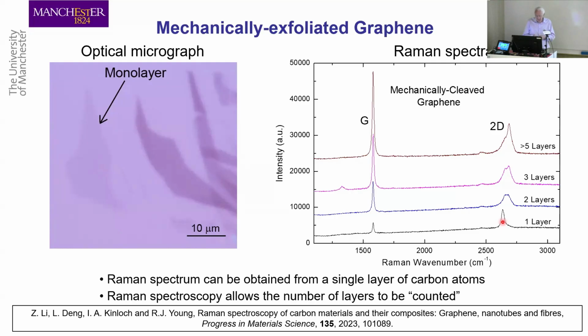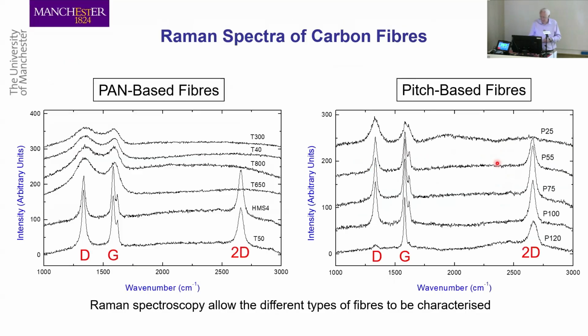So that was the first thing that we'd done. And we'd done this sort of work on carbon fibers before for many years. And we knew that for carbon fibers, these bands in the Raman spectrum, these peaks in the Raman spectrum were sensitive to stress. And we were interested in what the situation was in the case of graphene. So this is some of our really old work on different sorts of carbon fibers. These are PAN-based carbon fibers, standard carbon fibers, the sort of carbon fibers you see in modern aircraft. And they have these 3 bands in them.